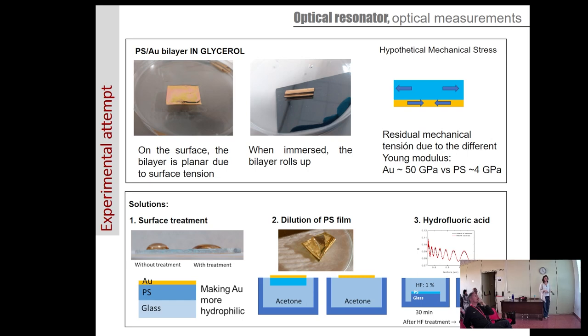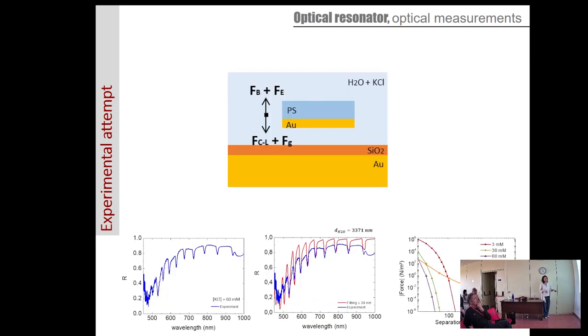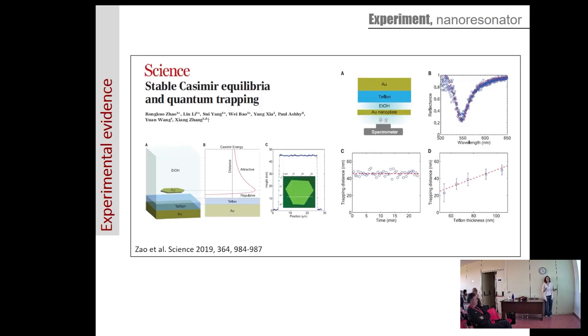We tried different solutions, but in the end, this is what we measured, this is what we fitted, and this corresponds to one order of magnitude larger than what we expected from our design. So our design was done for something like this, and this is what we were measuring. We also checked the effect of electrostatic forces and so on, and when we were dealing with this, then it happened.